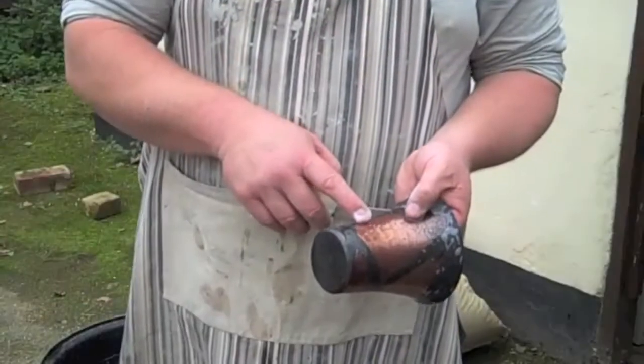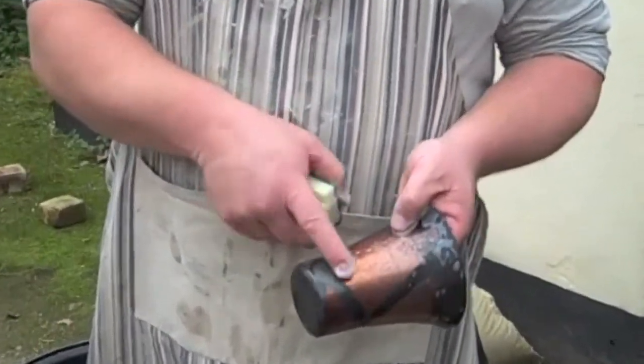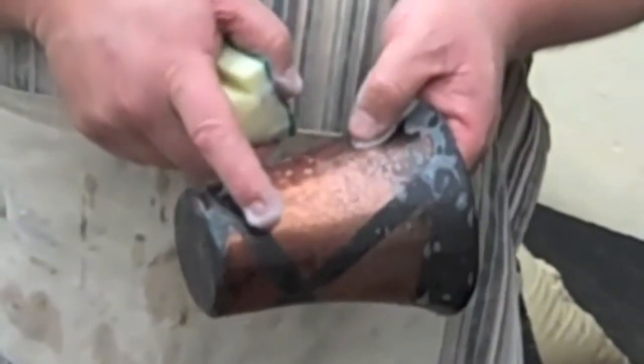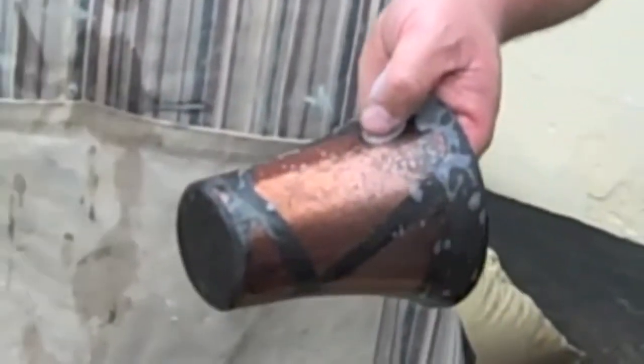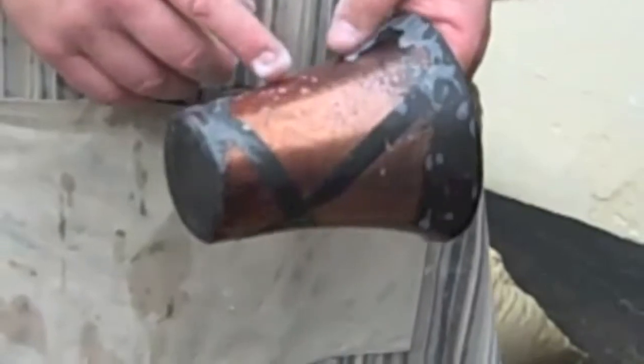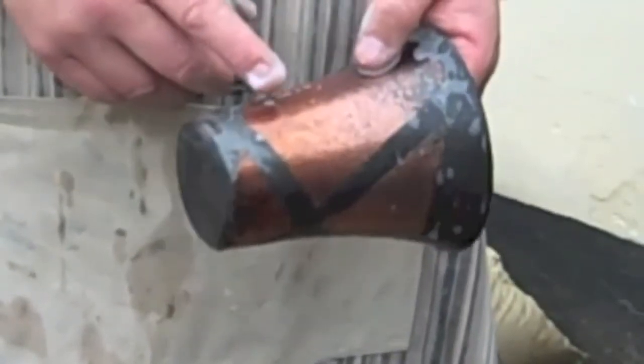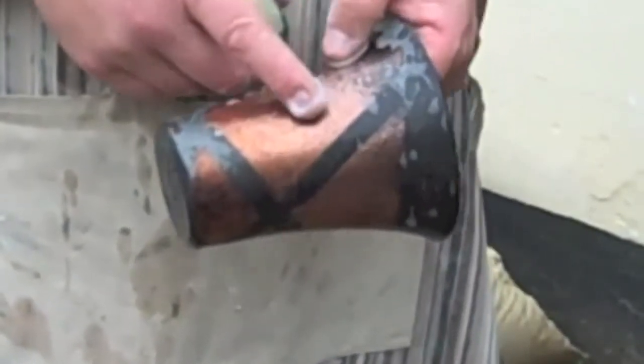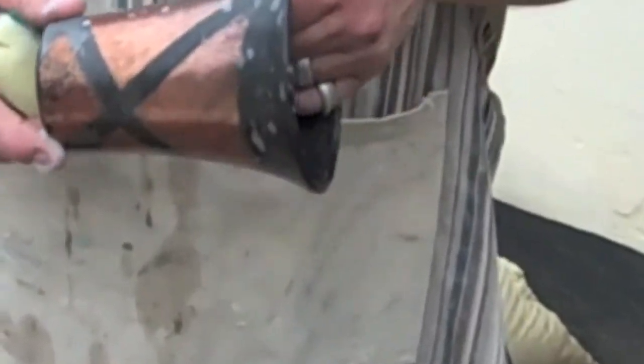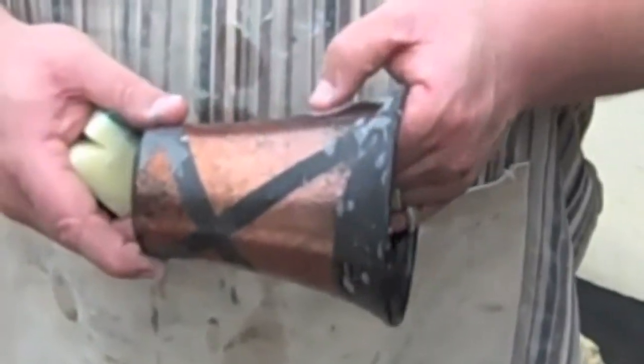So that has been reduced really heavily, which is giving us the really bright copper colours. You'll notice when we go through the day, you'll see some that are more green and blue, which have been oxidised a little bit more. But this one was the first one out of the kiln and straight into the sawdust, which is why you've got that bright copper all over it.